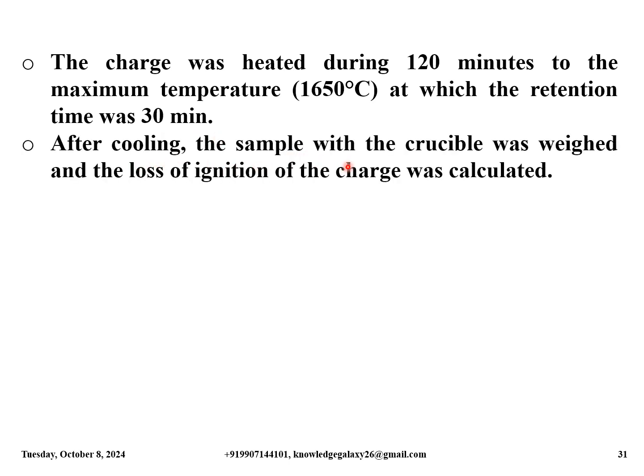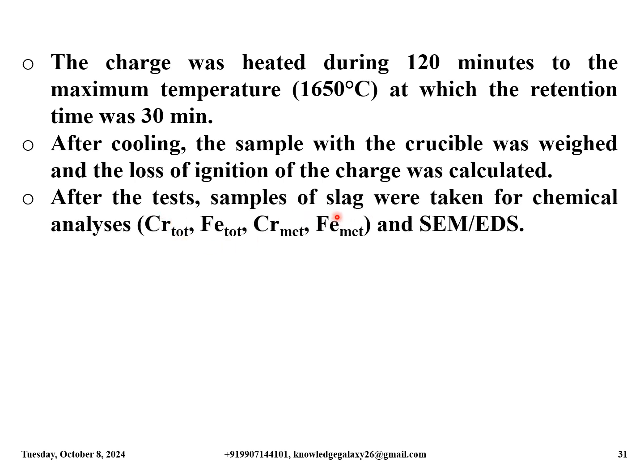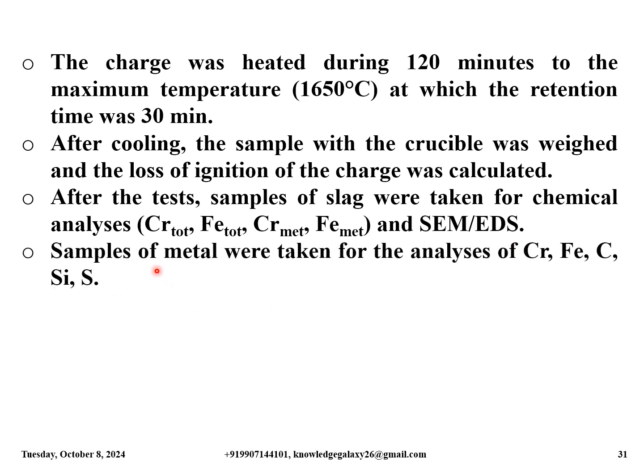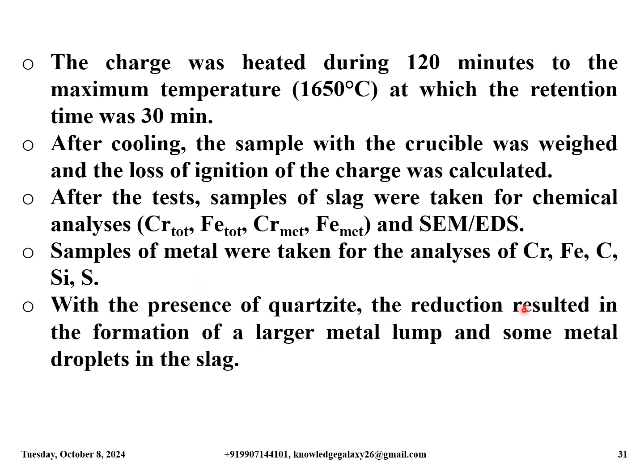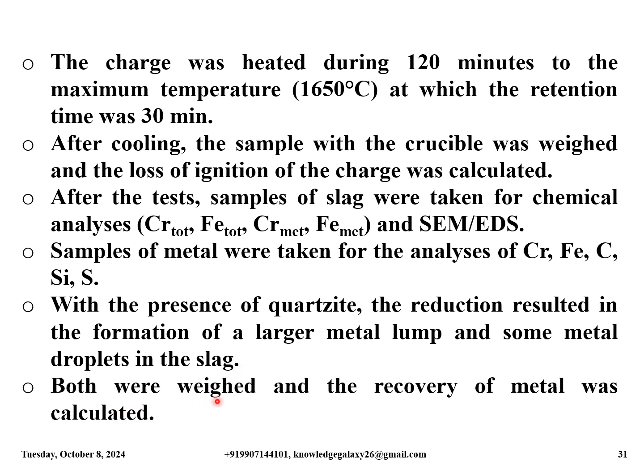After cooling, the sample with the crucible was weighed and the loss of ignition of the charge was calculated. After the test, samples of slag were taken for chemical analysis for chromium total, iron total, chromium metallic and iron metallic, and SEM or EDS. Samples of metal were taken for the analysis of chromium, iron, carbon, silicon and sulfur. With the presence of quartzite, the reduction resulted in the formation of a larger metal lump and some metal droplets in the slag. Both were weighed and the recovery of metal was calculated.